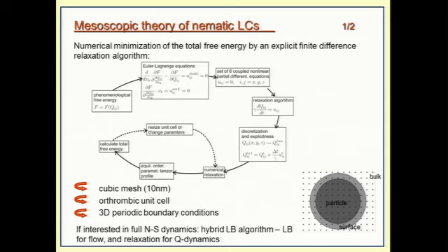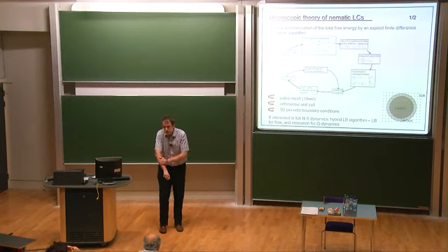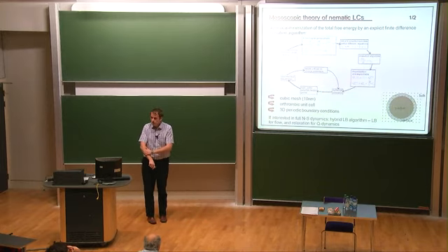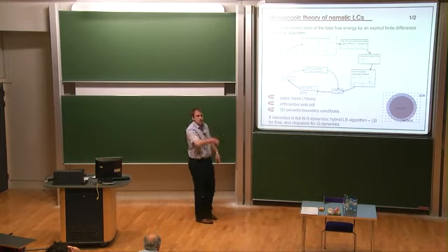But again, I keep getting questions. Why do you use the relaxation algorithm? You just describe sort of a diffusive dynamics to your system. Well, the reason is that this dynamics mimics the real dynamics of the system. The only thing you're neglecting is material flow. So you can solve these equations with any other solver.